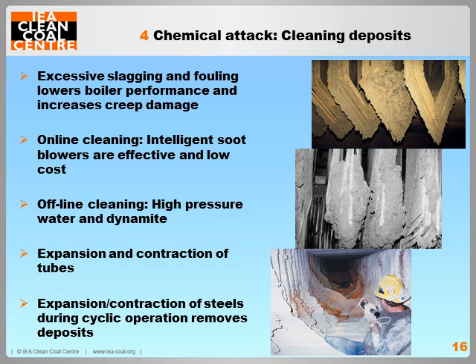Typical payback periods for some plant can be less than 1 year, and also this online cleaning technique can eliminate the need for offline boiler cleaning for up to 20 years. An unforeseen advantage of cyclic operation is the fact that cold starts expand boiler tubes by up to half a millimetre. This can effectively dislodge the deposits, which again reduces the need for offline cleaning.